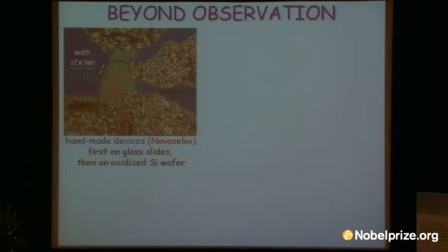That's a flake of graphite the size of a hair, 50 microns in this direction, 100 microns in this direction, and with a toothpick you put a silver paint contact to this device. This was done by Kostya, and it really requires experimental skills. I know only Kostya, myself, and maybe one or two more people with whom I ever worked who could do such small things. So what was surprising, and this is August 2003, is that those devices worked.